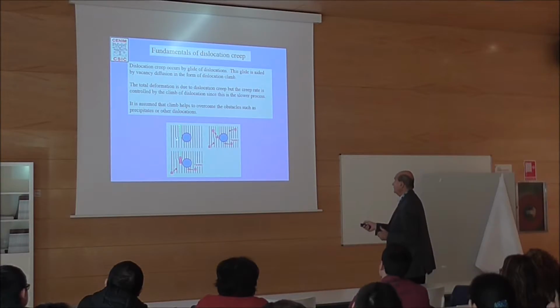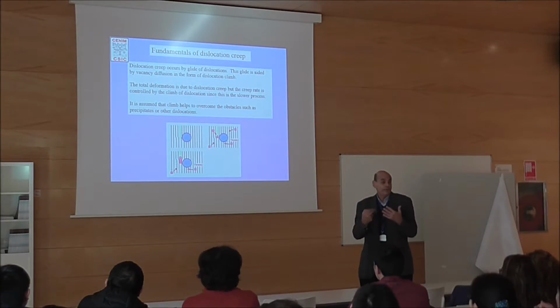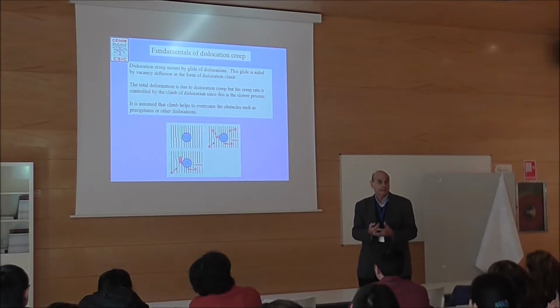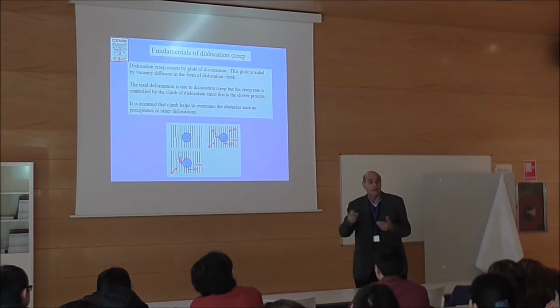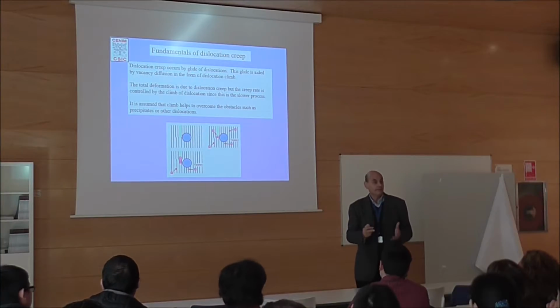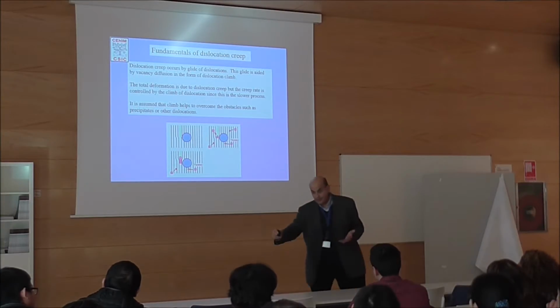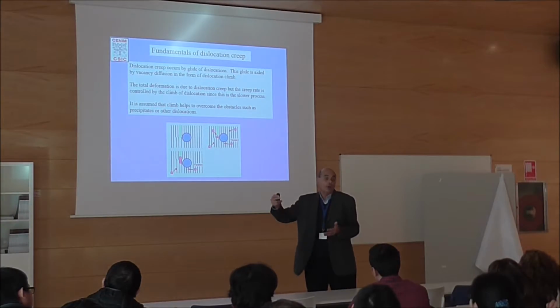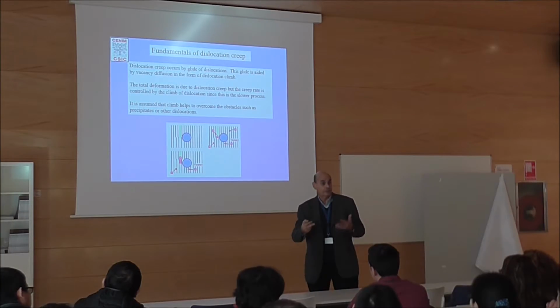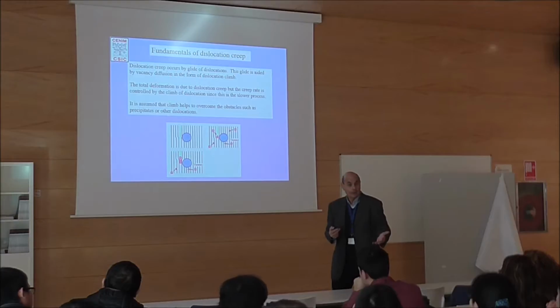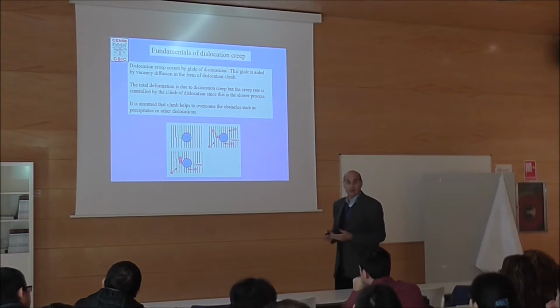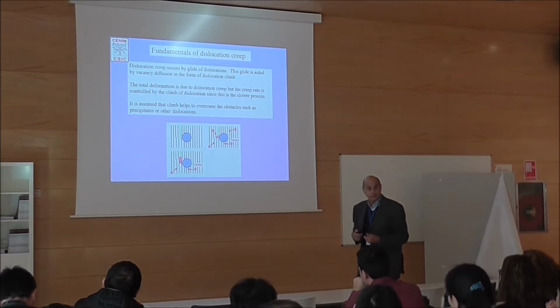It is climb. This is the dislocation obstacle, and it's climbed by diffusion of vacancies to the core of the dislocation. And we have diffusion, and because climb is controlled by diffusion, the strain rate... We have 2 processes: slip, and then we have climb, which is slower. Since they are interdependent, the slowest is controlling. The slowest process is climb, and that's why the strain rate is dependent on diffusion, self-diffusion.